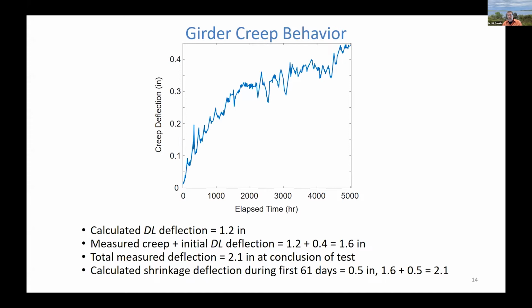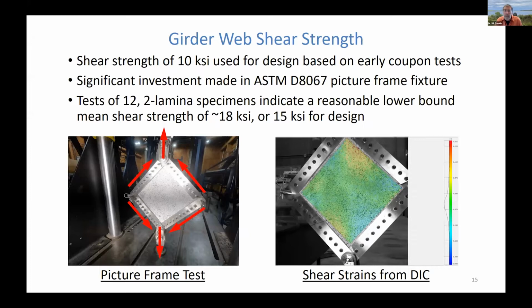So at the end of the day, this is actually very similar to a concrete girder bridge where it's pretty typical to specify a camber of at least 1 times the dead load deflection to account for creep. Sometimes it's a little bit more, but that's sort of a minimum value that I recall from my time in practice. Now, another really important aspect of design is girder web shear strength.